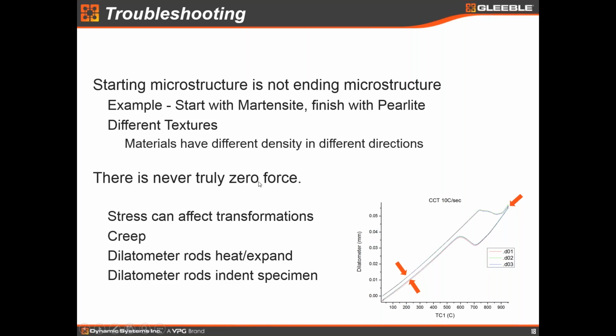The other thing is that there is never truly zero force in a dilatometric experiment. We discussed how we clamp the sample into copper water-cooled jaws to get great cooling rates and maintain isothermal planes. Obviously, when I clamp that sample into the jaws, I am putting a little bit of force on it. We allow the sample to expand and contract in the Gleeble using very low friction bearings, but we're still having to conduct electricity to that sample. So there's a little bit of spring tension in the cabling that we try to reduce as much as possible, but there's never truly zero force on a dilatometric sample, because even if I could achieve a truly frictionless environment, the sample itself has weight. That stress can cause a little bit of directionality in some of the transformations, and also a little bit of creep.